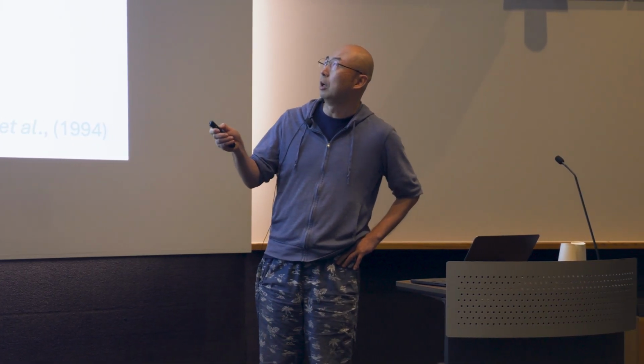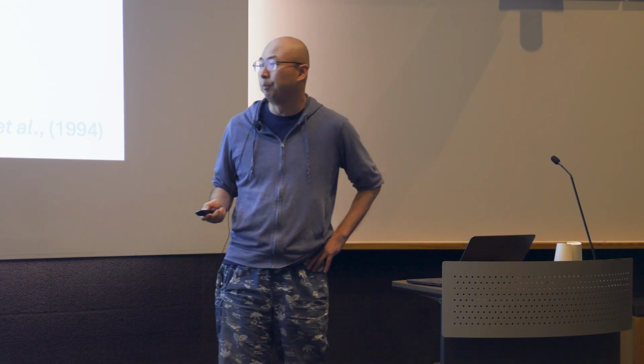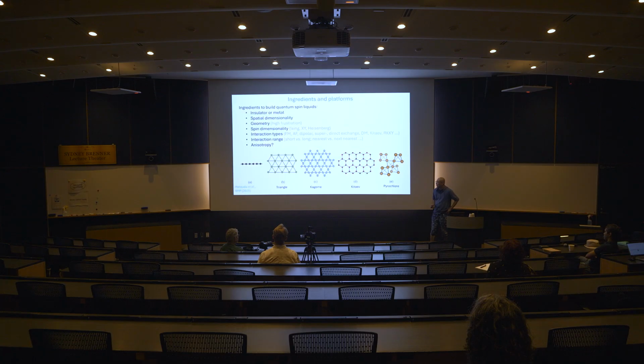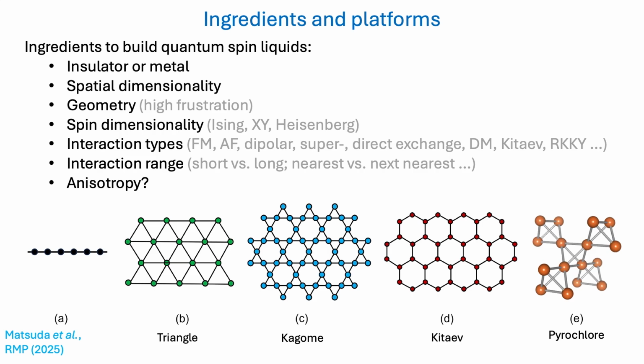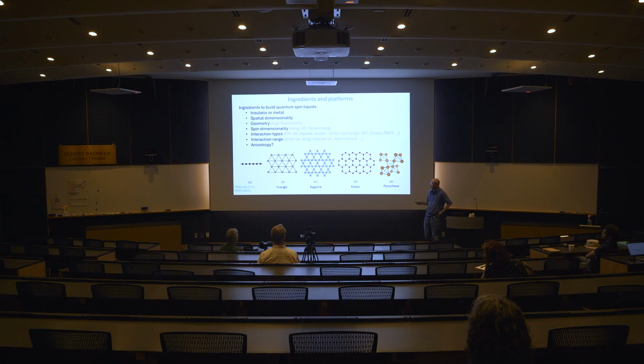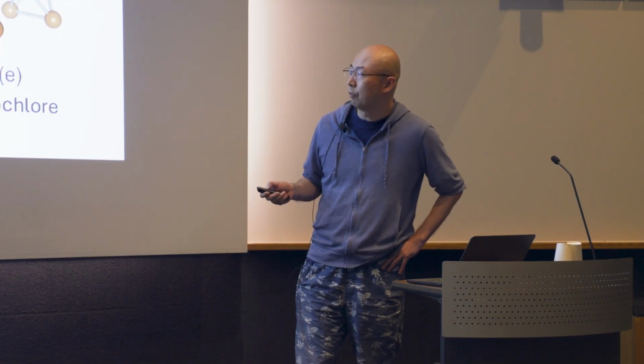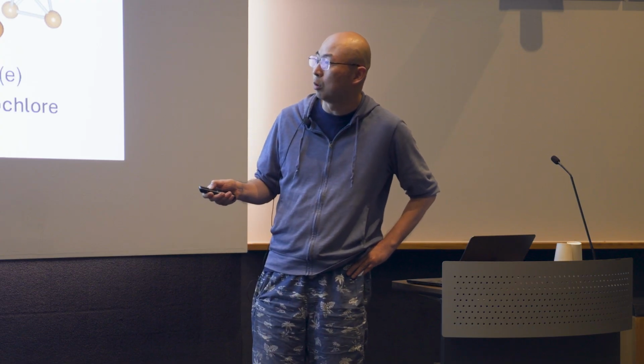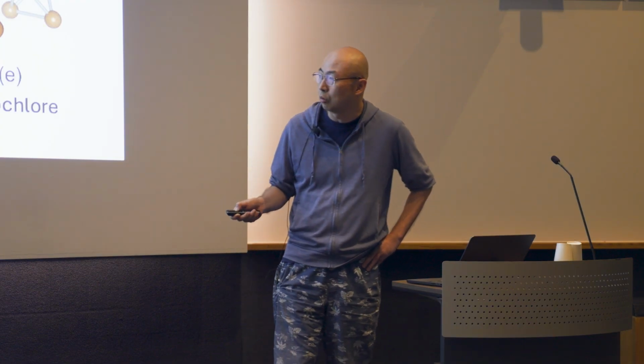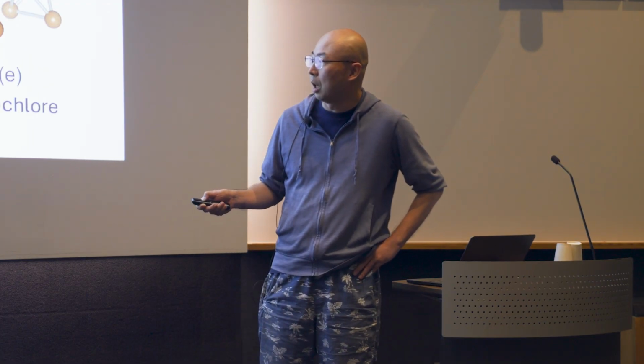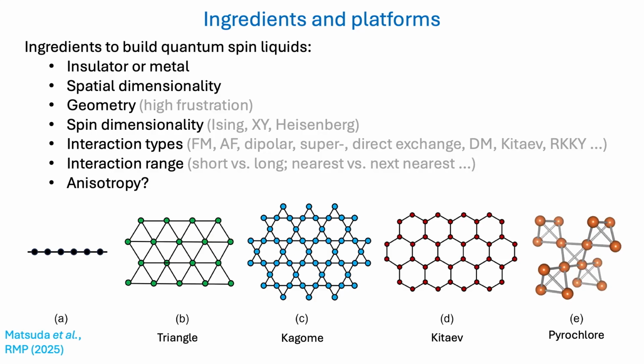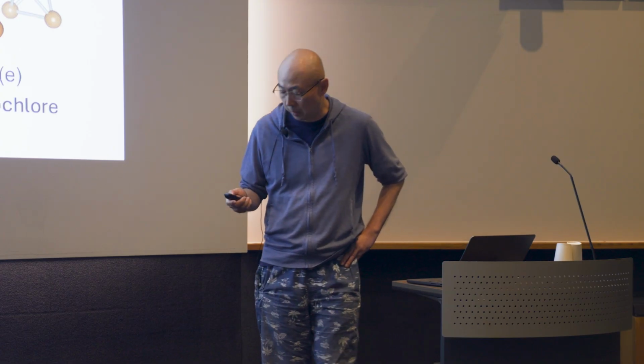Of course, chemical disorder is another thing, which depends on the sample quality. So we have a list of ingredients which can lead to a quantum spin liquid: either insulator or metal, spatial dimensionality, and geometry. Geometry turned out to be the most important thing, as you have to have a geometry which can potentially support spin frustration. The forms we know of are in 2-dimensional space. We talked about the 1-dimensional story already. In 2-dimensional space, we have the triangular, Kagome and Kitaev lattices. And in 3-dimensional space, we have the pyrochlore lattice, which will be my focus point.